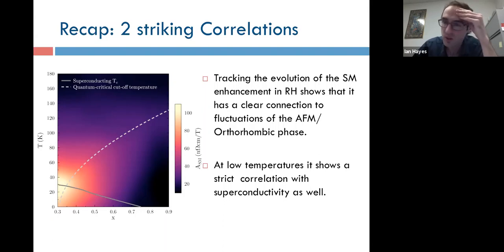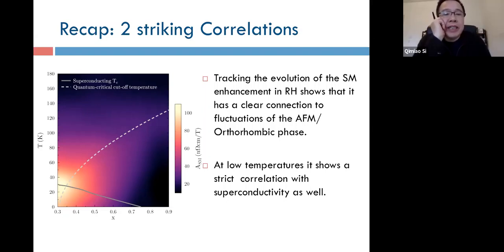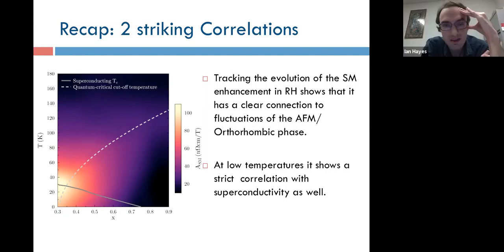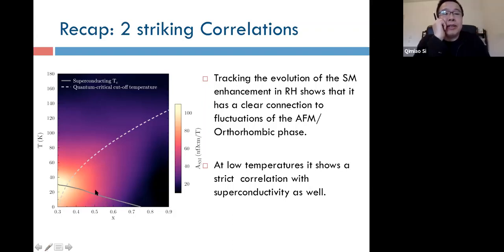Can you describe what accounts for that difference between vanadium doped chromium and the heavy fermion material? Yeah, it's tied up with the very drastic Fermi surface change on the two sides of the quantum critical point that happens in heavy fermion systems, that doesn't happen in the more conventional spin density wave quantum critical point. What's most striking here is that it doesn't seem to sharpen up totally. No matter how low you go in temperature, there's some finite width here, which seems to characterize the superconducting dome, which might be related to the truncation of the quantum criticality on the temperature axis.